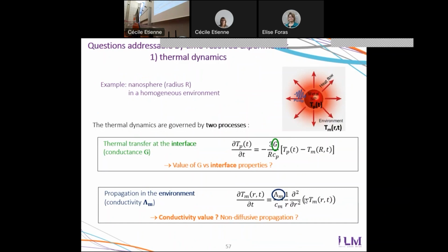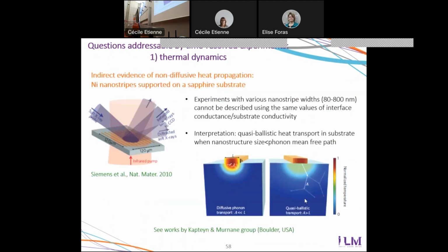And here, we can estimate the conductivity, but we can also see whether there is a signature of non-diffusive effects. It's something that we didn't see yet in our experiment in Lyon, but which was seen by American researchers in systems in which they performed time-resolved experiments on arrays of nanolines. What they found was that for very small nanolines, they could not use the same model as for much larger nanolines. And the interpretation was that the nanolines are too small for thermal transport below the nanolines to be assumed to be diffusive. It has become quasi-ballistic.